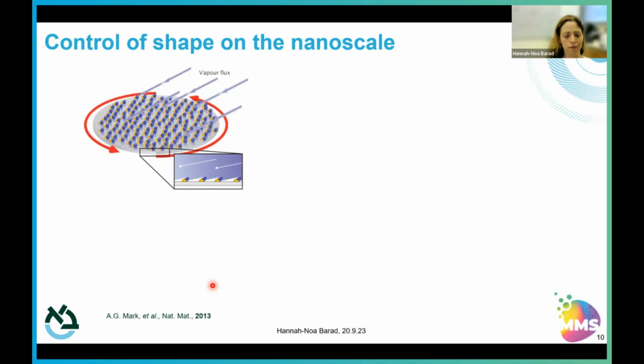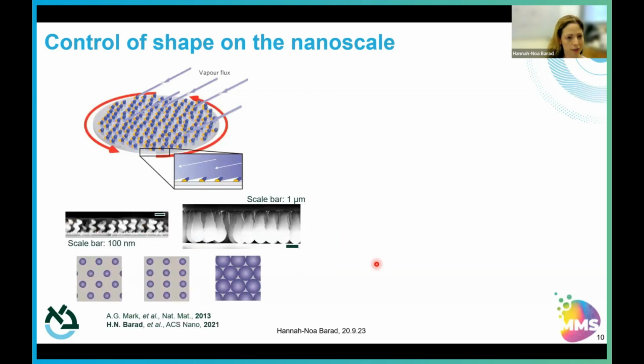So in order to form material libraries, the standard method for doing this is, for example, sputtering, a physical vapor deposition method, which is continuous and very easy to make these material libraries. So we can control nanoscale also using physical vapor deposition to form a variety of different types of structures. And this is done using glancing angle deposition, which I will explain shortly.